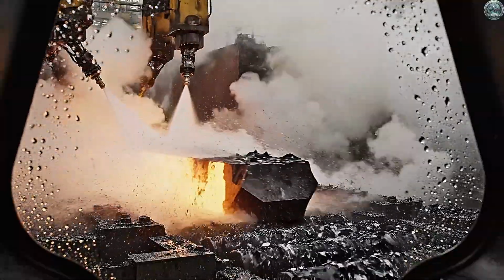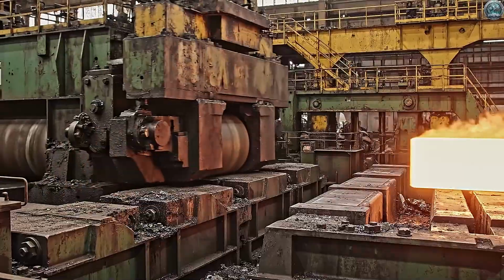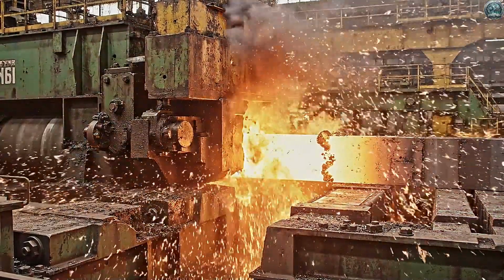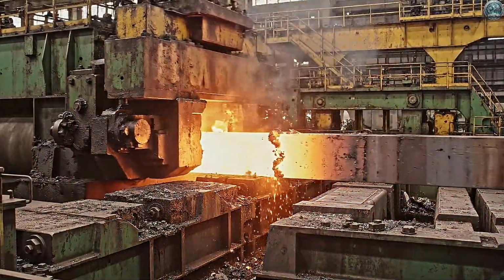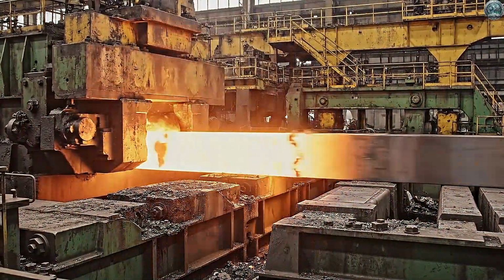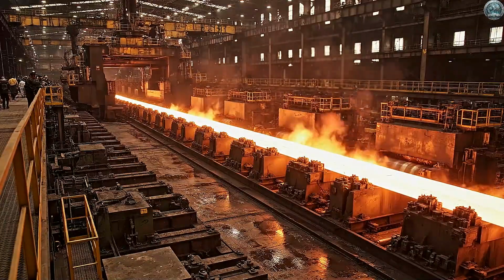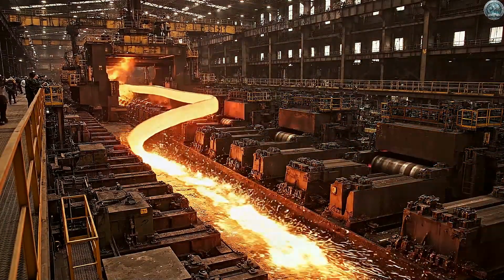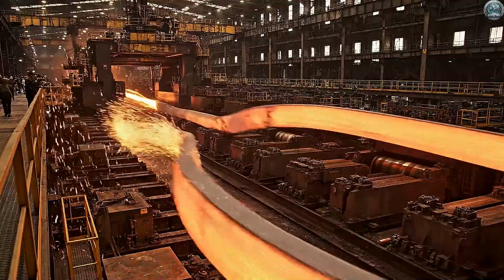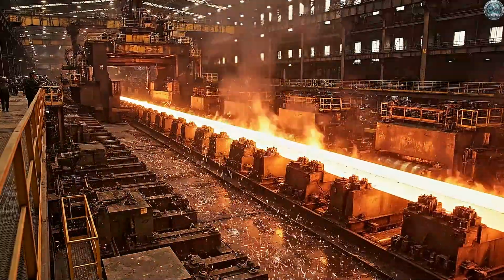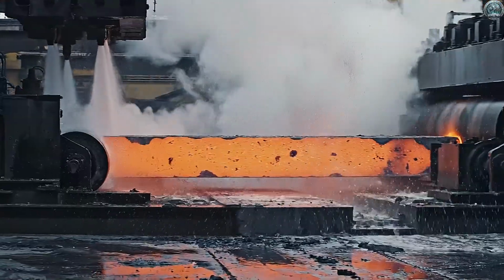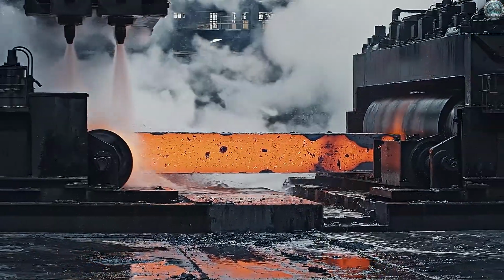High-pressure water blasts away the oxidation scale, leaving a pristine surface for rolling. The roughing stand begins the reduction process, squeezing the massive billet into a longer shape. Thinner, longer, faster. The steel transforms into a glowing snake, racing through the mill. Water cools the rolls as the speed increases, creating a battle of fire and water at every stand.